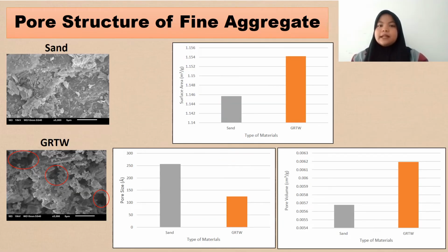For the SEM analysis image, the GRTW sample shows some pores that existed compared to the sand sample. Surface area for sand is less compared to GRTW. Because of its high porosity, the calcium silicate hydrate responsible for the hardening reaction has a huge specific surface area when hydrated cement hardened. Single point desorption total pore volume of the pore is less for sand than GRTW.